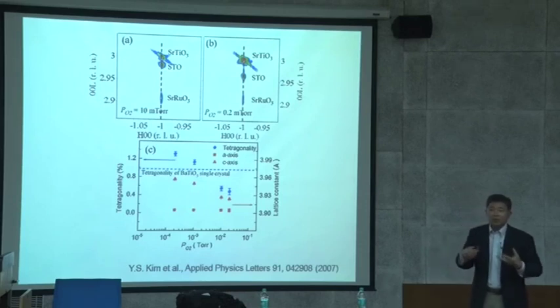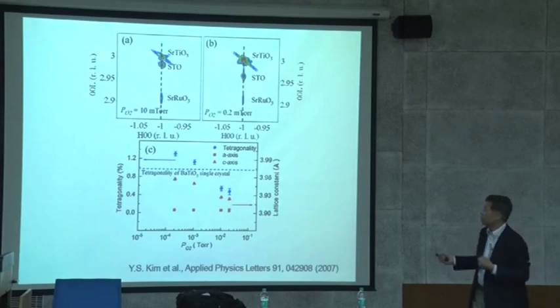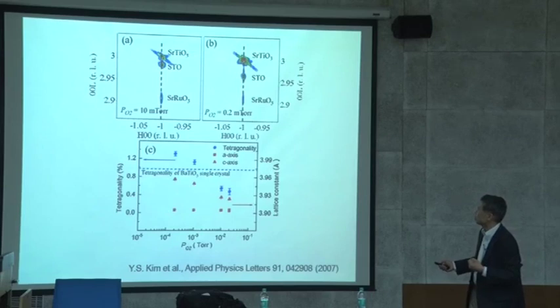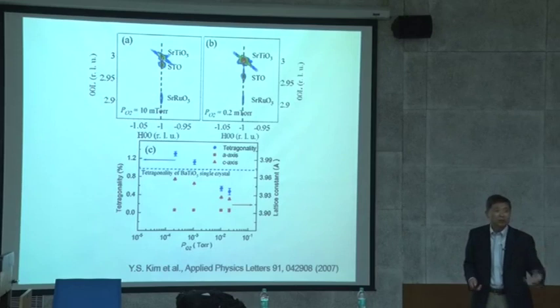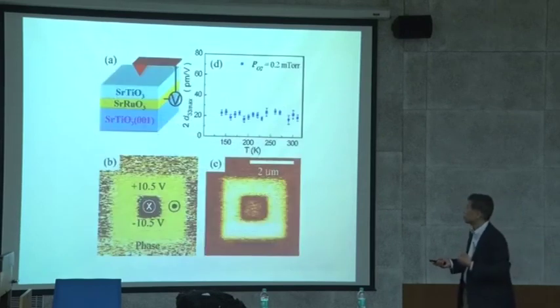And so this large off-stoichiometry can create this, and it's a barium titanate single crystal compared to this, with a large tetragonality, you can actually see that. And you can see when you deposit at low pressure oxygen versus high pressure oxygen, the low pressure one has more defects because you have oxygen vacancies creating volume expansion, which is the main reason, and then creating this ferroelectricity is a lot of oxygen vacancies. Okay. So that's what they reported.